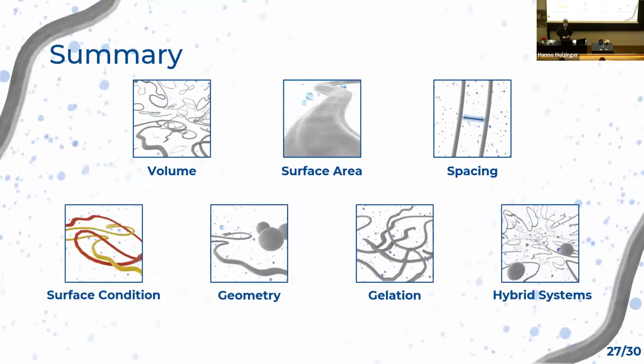Now, to summarize, I've looked at water diffusion in different CNF dispersions, hybrid systems, and other nanoparticle systems as well with spherical geometry, with several factors influencing the water diffusion in these systems. Increasing volume and surface charge reduces water mobility, while the surface charge itself affects the hydration layering around it, and therefore the effective volume that the water is affected by. The nanoparticle geometry and semi-flexibility amplify this effect with the dynamic contribution as we hypothesized, and lead to further slowdown